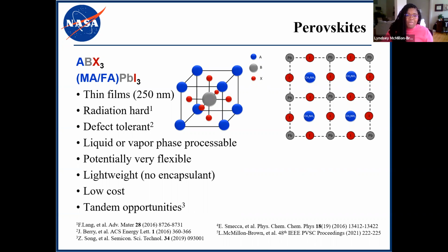including their really thin films. The active layer is around 250 nanometers. They're radiation hard, and what that means is after exposure to proton or electron radiation, they still have a high remaining factor and the devices still perform fairly well. They're defect tolerant, which is particularly special when we consider the current state of the art for space, which are crystalline silicon or crystalline gallium arsenide based solar cells. Due to their crystallinity, any vacancies or defects in their lattice will result in reduced device performance. But perovskites are a bit more tolerant to any errors in their lattice.